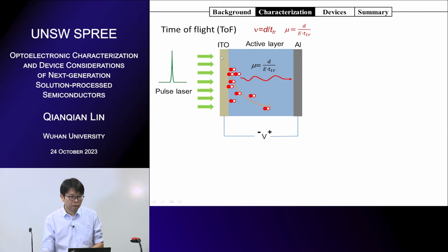We deposit 2 electrodes on each side of the active layer of the semiconductor, and one side is transparent, so we can photo-excite the semiconductor. We give a laser pulse of very short duration, we excite the semiconductor and generate a lot of carriers at the interface.